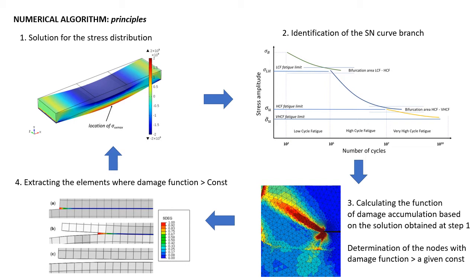It is important to outline that the local stress can be higher than the applied macroscopic stresses. This can lead to a switch between fatigue curve branches at different stages of the numerical calculation. The third step is calculating the damage function for each element and choosing the elements where the value of the damage function exceeds a given value.